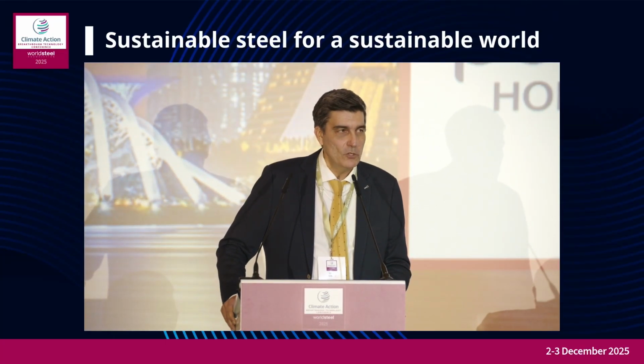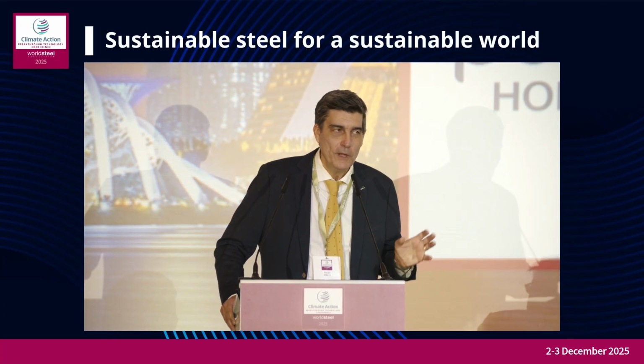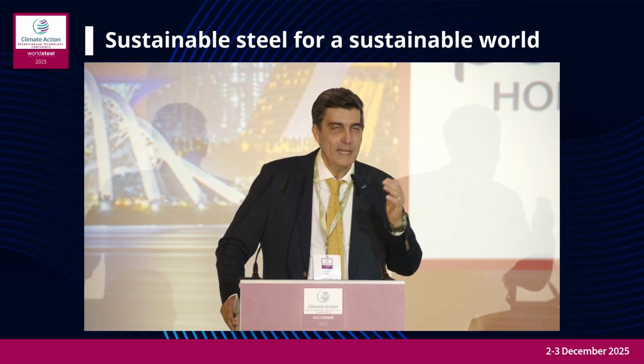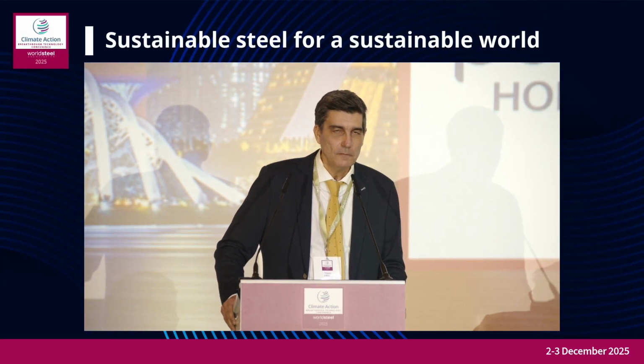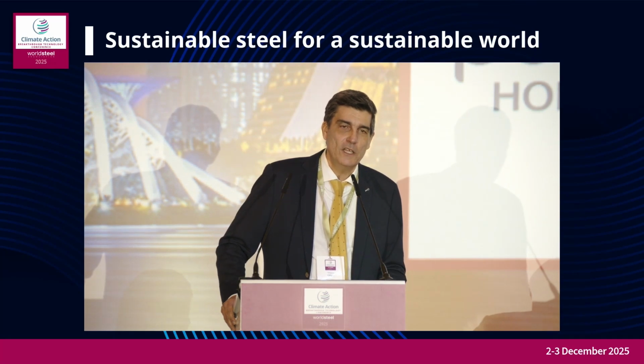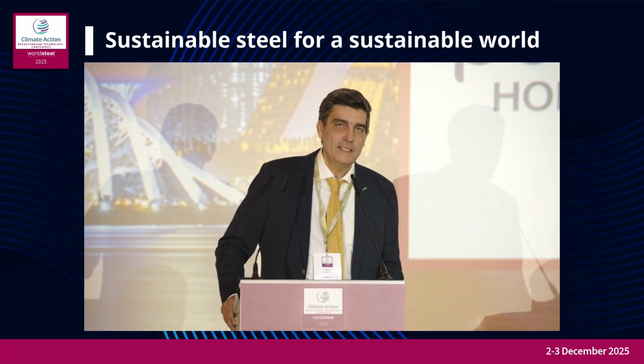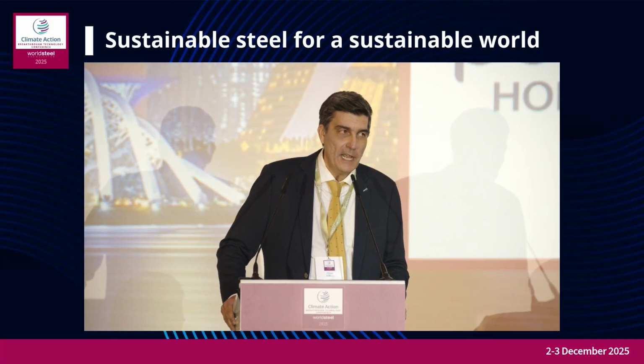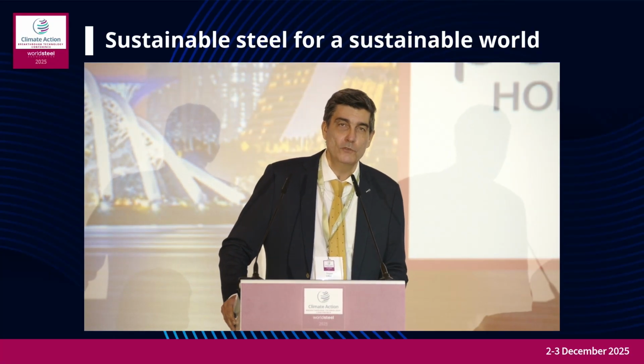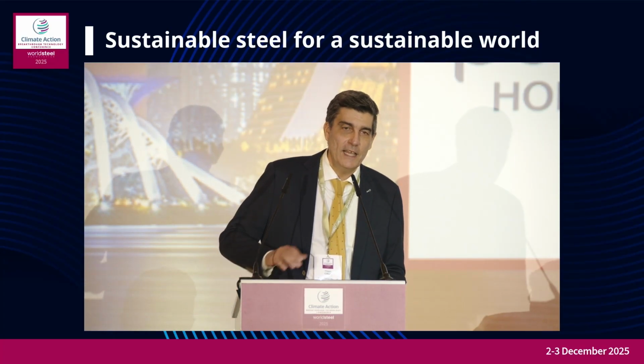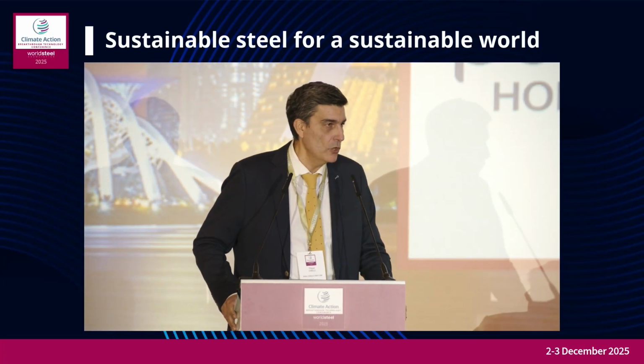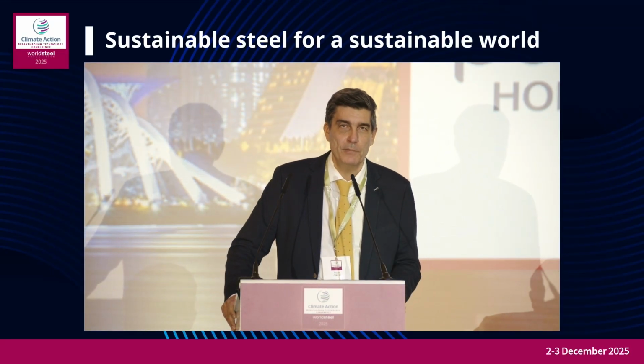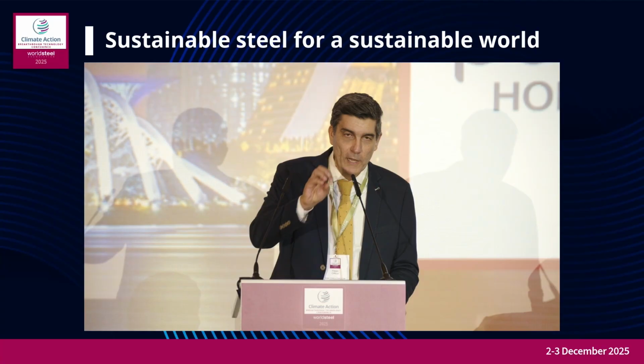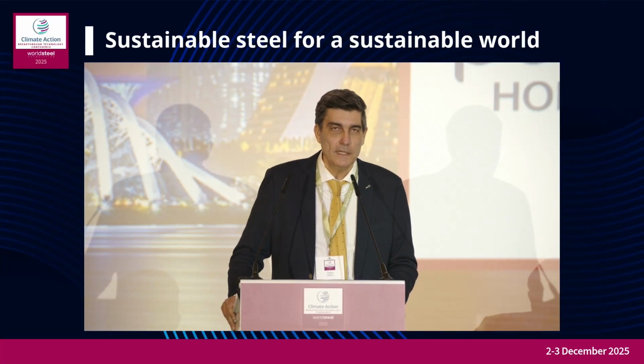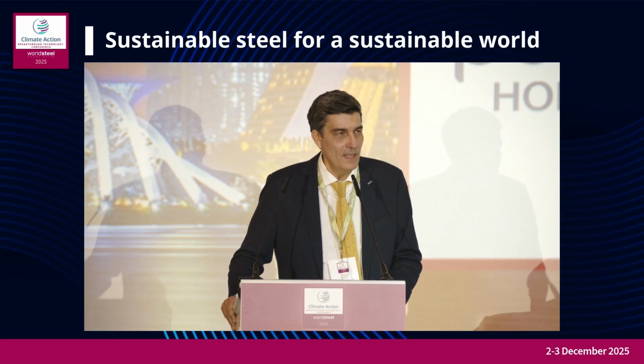Maybe we can share some more data, but if this is the evidence, we can focus the experiments on other topics. But what I can say is that an important aspect is what we are going to test, that in any case the effect of parameters. So, for example, we performed the test at 900 degrees. We see an interaction, which is negligible from the practical point of view. And now what we are going to perform is the same test at higher temperature, not only for academic curiosity, but to study if there is a strong impact on temperature, which means if there is a strong impact on local peak temperature. But it does not mean that necessarily there must be an effect.